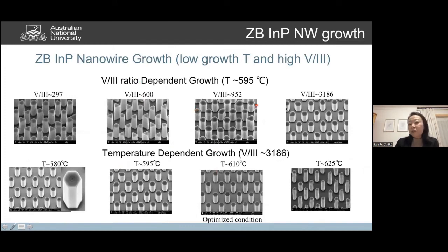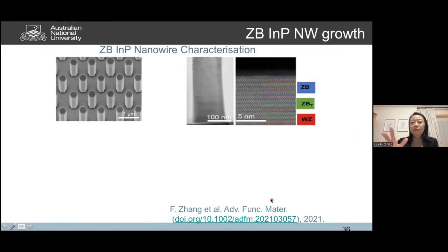So here's some further optimization. My student Fan Lu spent a lot of time optimizing the growth. We reduced the growth temperature, and he did a first investigation of the V/III ratio by increasing it from 80 to 3000. And by further optimizing the growth temperature, he can create this very nice hexagonal shaped nanowire, which has a very uniform shape and no distortion of the different shapes.